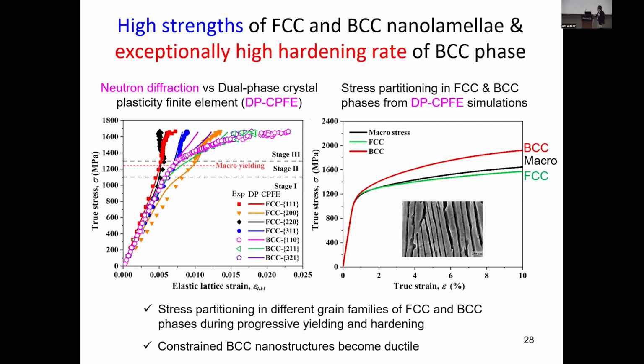In this case, we used neutron diffraction at Oak Ridge to measure the lattice strain responses of different phases, and for each phase and for different grain families. So you can see, we have more results. We also need to develop this dual-phase crystal plasticity finite element model to predict these lattice strain responses. More importantly, this enables us to partition the load in the FCC and the BCC phases.